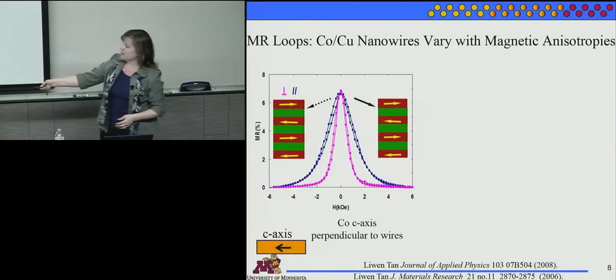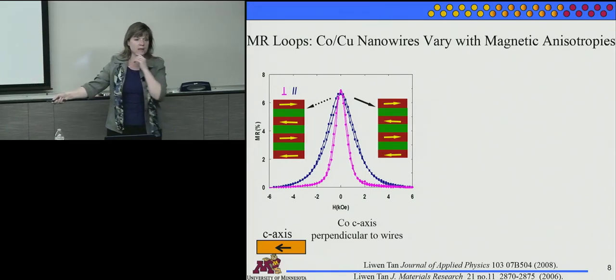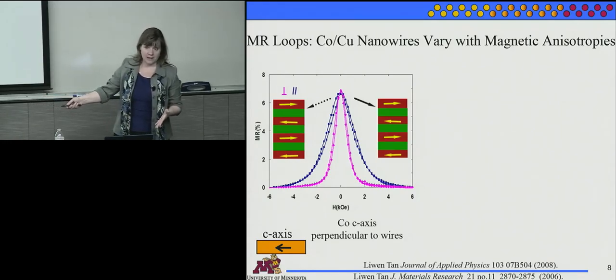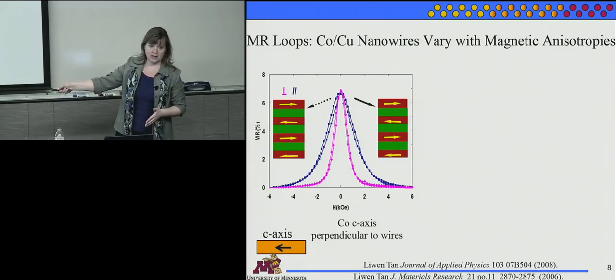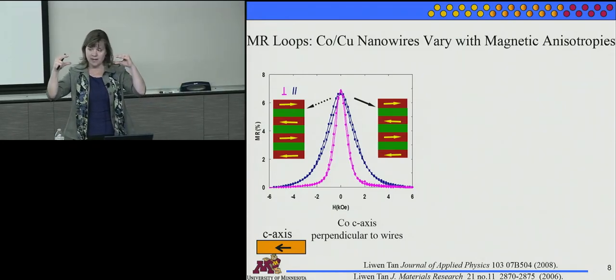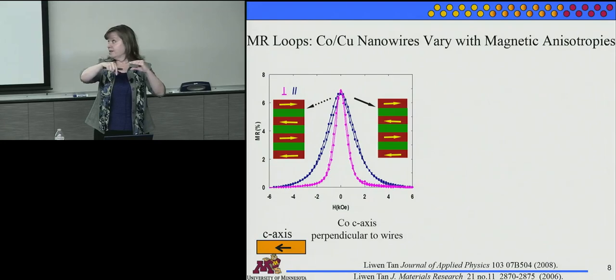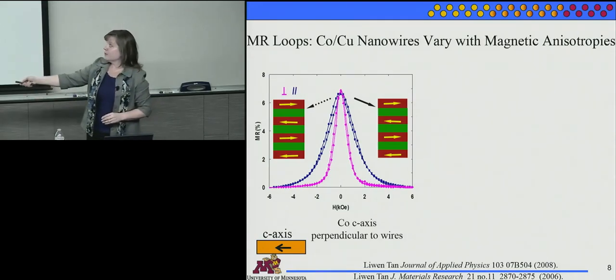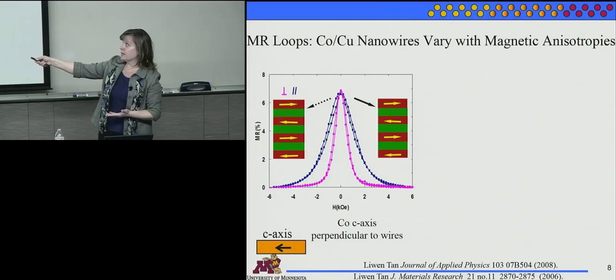And what happens? Well, if I have the C-axis, cobalt, you'll remember from the other talks, has a very high crystallographic anisotropy. But I'm going to grow a pancake shape. So the shape anisotropy is going to be a pancake, and my crystalline anisotropy, in this case, is along the pancake. And what you can find is that the resistance, well, up here it's pretty high because the layers all go back to being antiferromagnetic. Then I apply a field, and they're aligned, so the resistance drops. Then I take the field away, they're antiferromagnetically coupled again, so the resistance goes up. Then I go the other way, and so on. So I get an increase in the resistance when I'm at 0 because they're antiferromagnetic there.